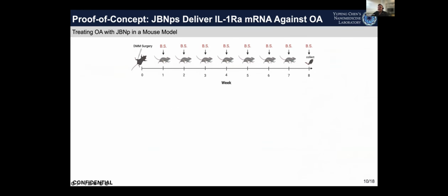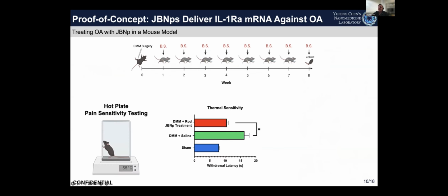We then continued to pain sensitivity testing, where we understand that in a healthy state, the mice are quicker to sense stimuli and react than in a state where pain from cartilage degradation is making it more difficult for them to sense stimuli or other pain. So first, on hot plate testing, the treatment group mice responded much quicker than the non-treated mice, which was very similar to the response of the healthy control group. This tells us that the treatment group was not experiencing more pain than the healthy control group, and it likely did not have degenerated cartilage.